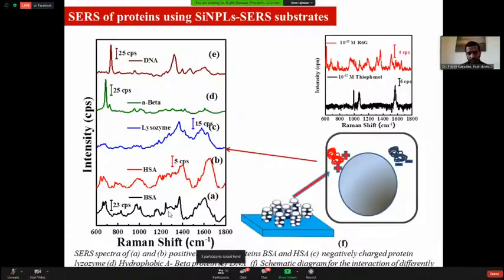First we checked some proteins like BSA and HSA. Those are structurally very similar proteins, but yet we could differentiate them using the surface enhanced Raman spectroscopy of this silicon nanopillar based sensor. And lysozyme and DNA, which are other important classes of biomolecules, we could detect using this sensor. And amyloid beta, which is the protein present in Alzheimer's disease, is also detected by the sensor. We have also checked the detection limit of the sensor, which is 10 to the power minus 12 molar. It is sensitive up to 10 to the power minus 12 to minus 13 molar of these analytes.